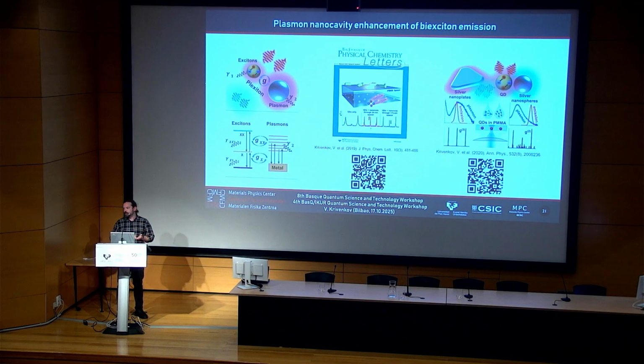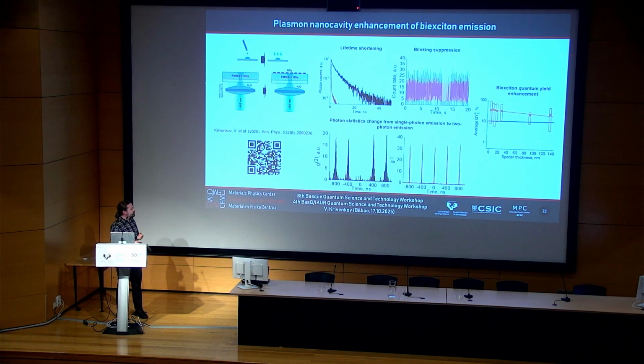So we can produce very efficiently photon pairs, still not entangled, but with a quantum yield of the biexciton transition very high. We achieved almost 50%. But at the same time, we change the statistics of the photon emission. We change from the single photon emission to the multi-photon emission, for emission of photon pairs.